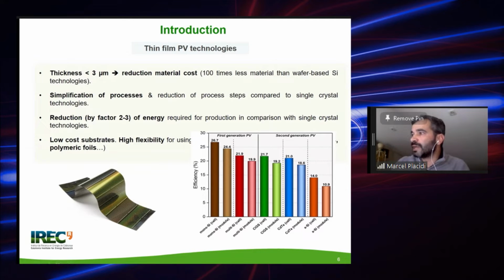Also, if we look at the efficiency achieved by thin film materials, here we can see for CIGS and cadmium telluride that right now the efficiency is a bit higher. It's around 23%, so we are getting close to the efficiency reached by silicon solar panels. So this is also good news for the thin film technology, which is approaching the silicon efficiencies, but at a lower price.